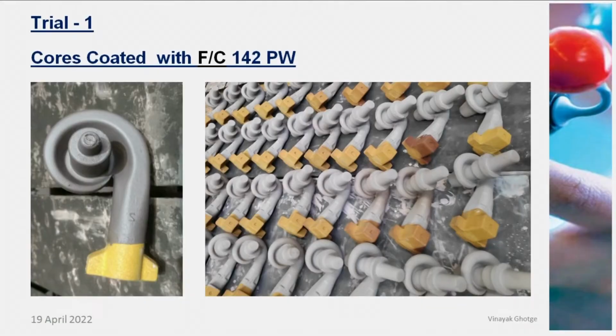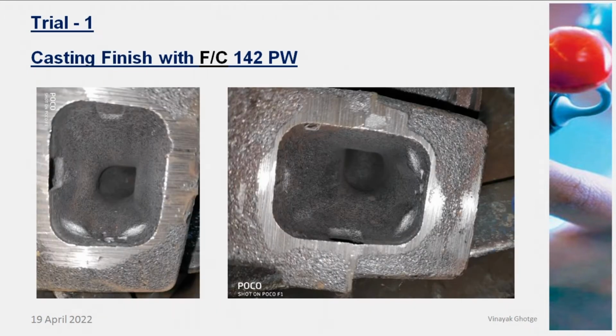And the wet film thickness we got was around 225 to 250 microns. These are the cores coated with powder coating made in situ. And this is the casting photograph, where you can see the clean casting.